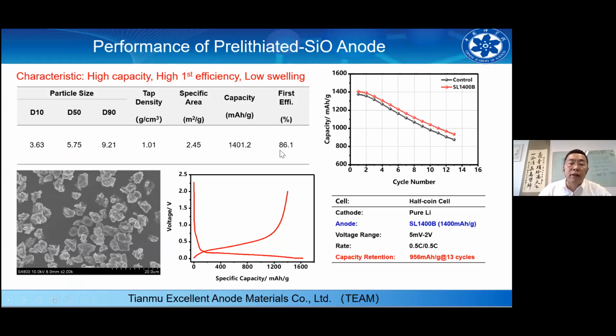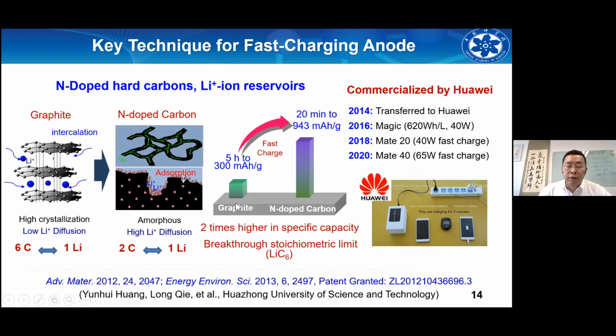And for the silicon anode, the research progress still continues. After pre-lithiation at the material level, the first Coulombic efficiency, capacity, cycle life and volume expansion can be controlled, and it can be used for real batteries. This is very important, to do the pre-lithiation at the material level. And also for the faster charging anode, the group from Huazhong University developed nitrogen-doped hard carbon, which has been used for mobile phones. Currently mobile phone applications need a 5C to 6C charging rate. It is very important to change from artificial graphite to hard carbon to get high rate performance.